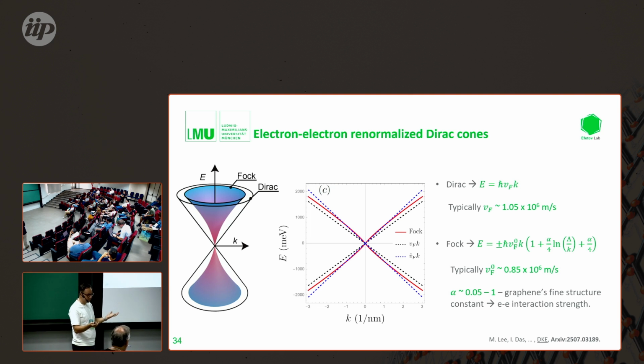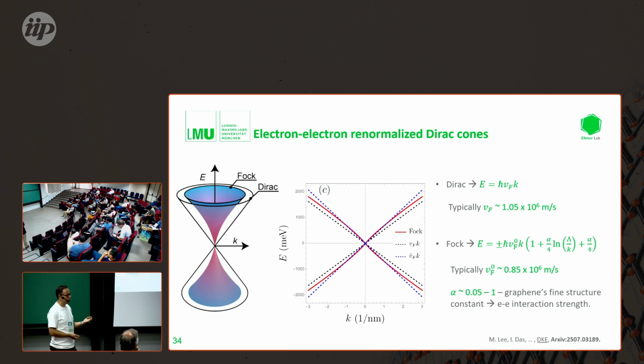So yeah, exactly. Phonons, for example, that's what I was saying, in addition to that, because it's probably a zero temperature calculation. Yeah. Also I have to refer to Shahal. Shahal at low temperature saw some phonon resonances connecting the Fermi surfaces. So they were able to see a phonon in that. At room temperature, of course, we have a lot of phonons. At low temperatures, they only see them because they're very sharp. But at high temperatures, of course, we have tons of phonons. So what the phonons do is they just broaden things. This is my assumption, yeah.